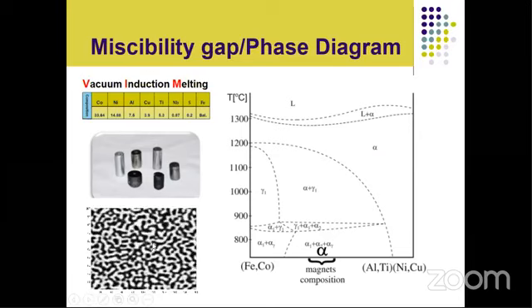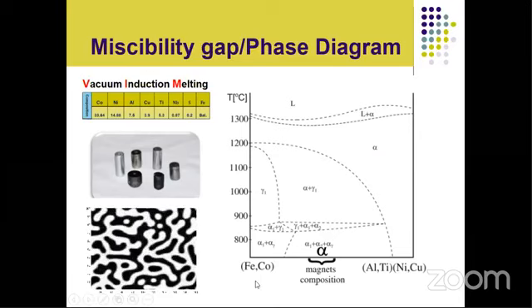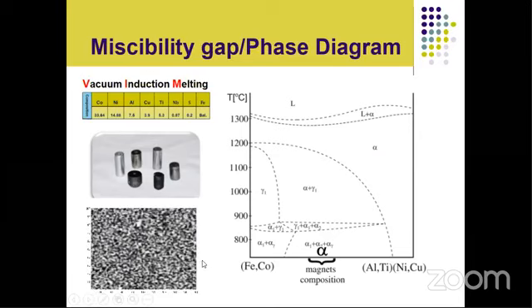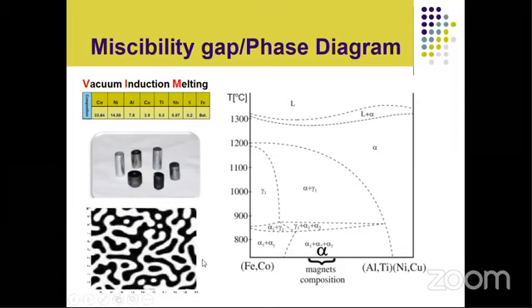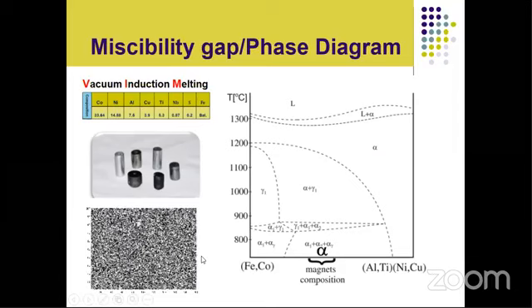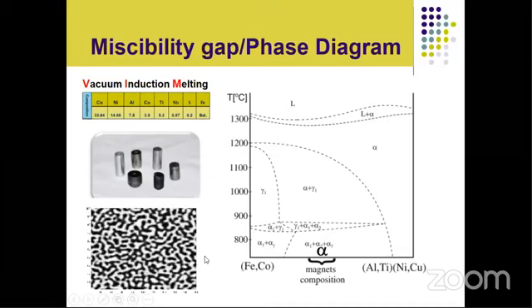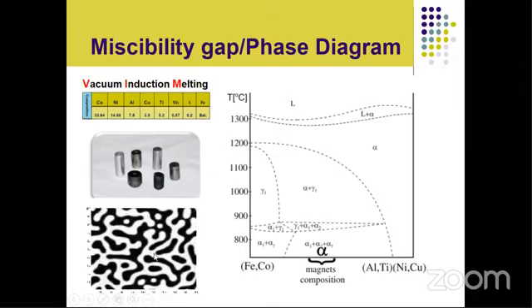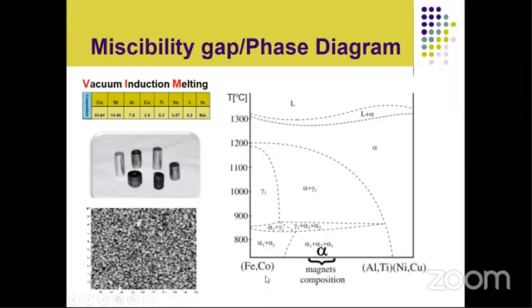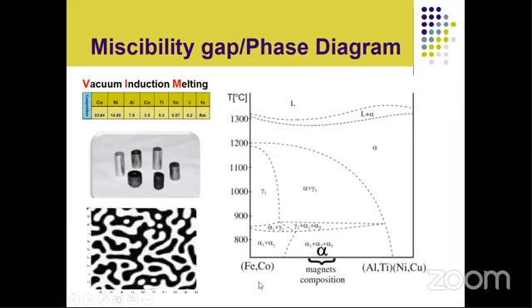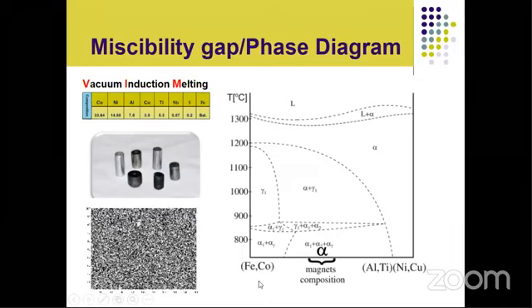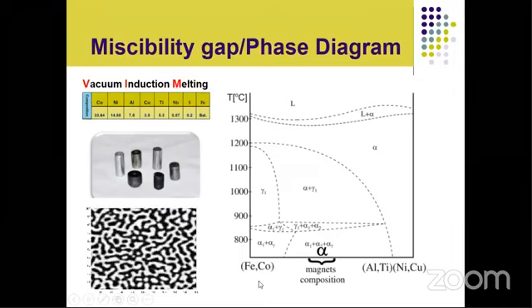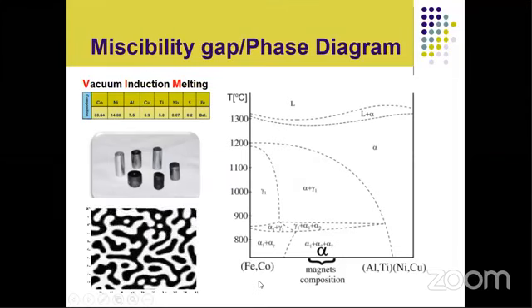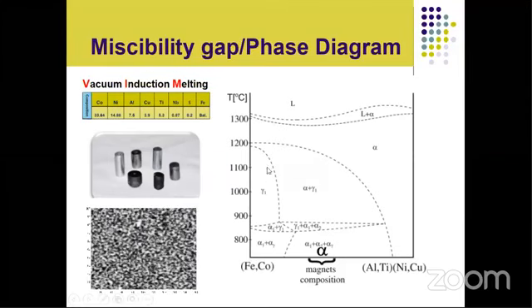So the composition gradient between these alpha 1 and alpha 2 phases is responsible for magnetic hardening and saturation or maximum magnetization of these materials. The higher the composition gradient between the alpha 1 and alpha 2, or finer the grains of alpha 1 and alpha 2, the higher will be the properties of the material, which includes coercivity, remanence, and maximum magnetization.